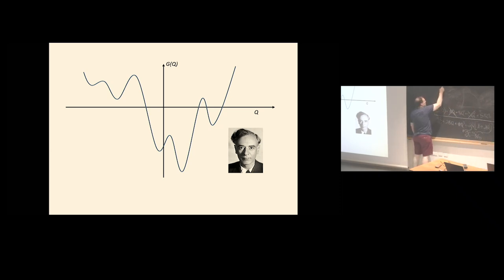So we're going to look for the second derivative of the free energy with respect to polarization. That's going to be equal to 2B plus 12Dq squared. And we know that that needs to be greater than 0. Okay. And I'm going to factorize this out because I'm just a bit lazy. So this could be B plus 6Dq squared.